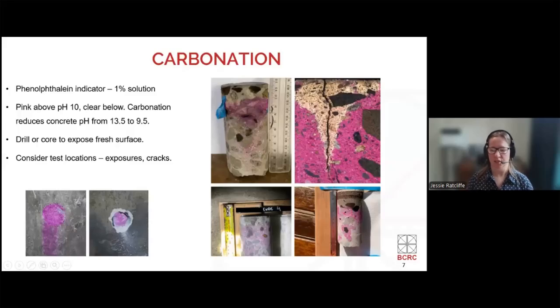The picture on the right shows you the importance of selecting your carbonation core locations using that initial inspection. So this one's been done over a defect that was noticed, and you can see that the crack has allowed the carbonation front to locally progress a lot deeper, and so we might expect accelerated deterioration in that area.